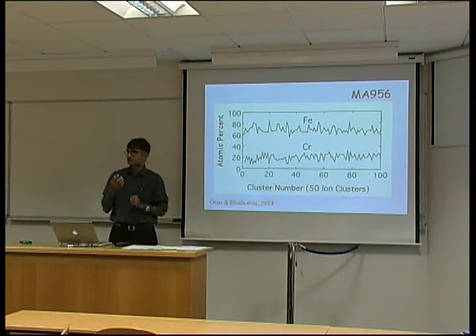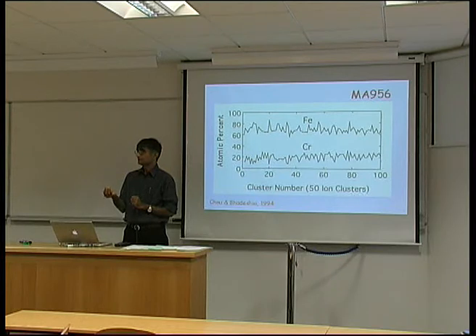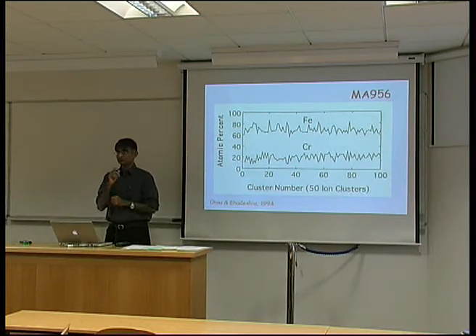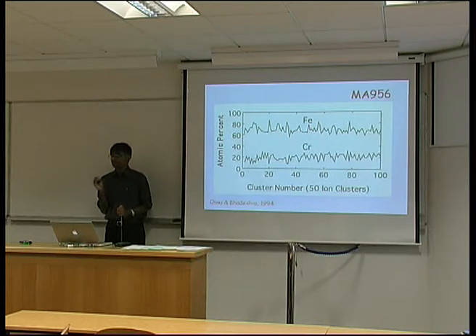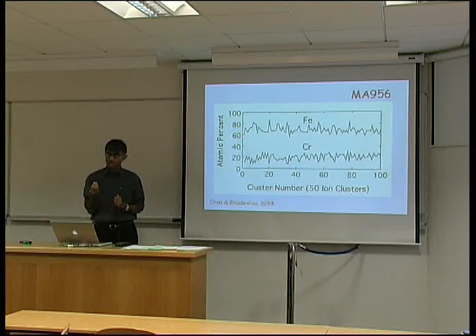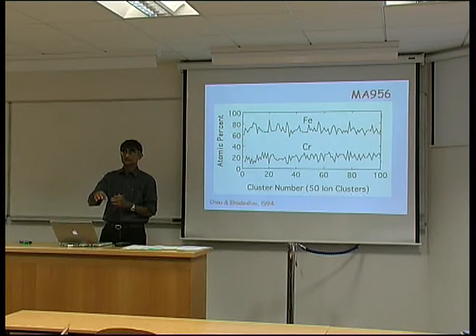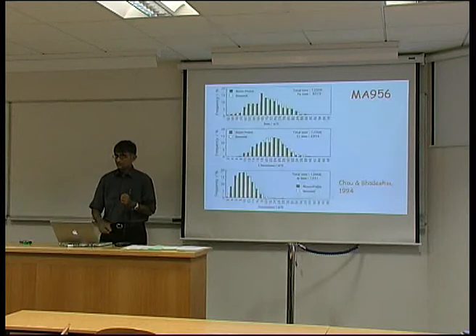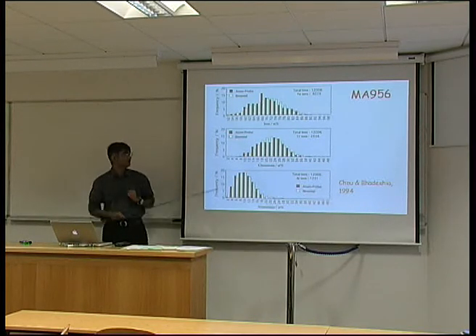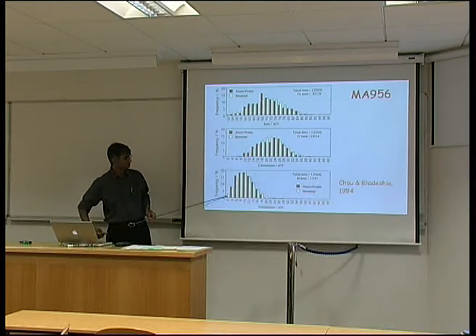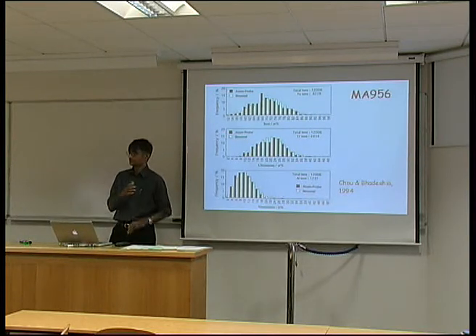If I just pick out one at a time, I would have a variation from 100 to 0. So we have to decide whether in a completely random solution, if I picked out 50-atom groups, I would get a graph like this. You might remember in statistics there is a thing known as a binomial distribution. Here is a comparison between the experimental results in black and a binomial distribution for 50-ion groups, and you can see they are not very different — for all three elements: iron, chromium, and aluminium. This means that yes, I have truly achieved a solid solution.